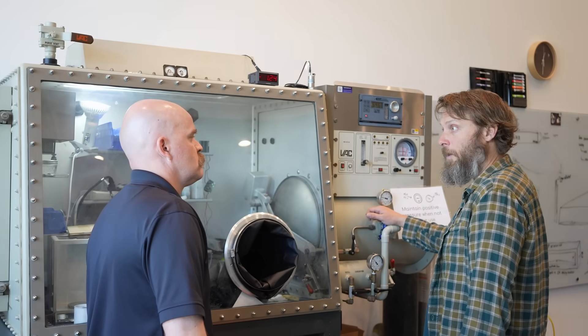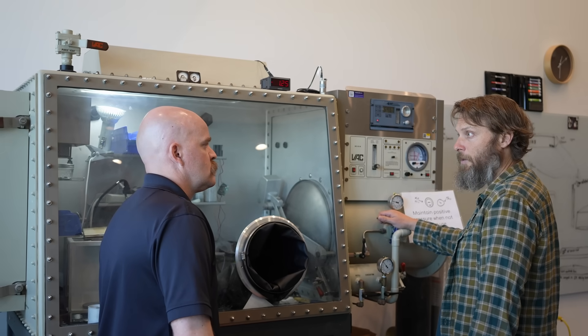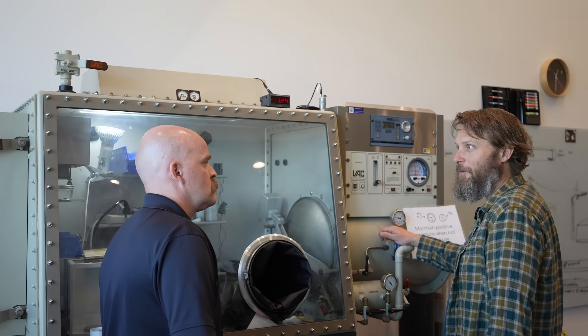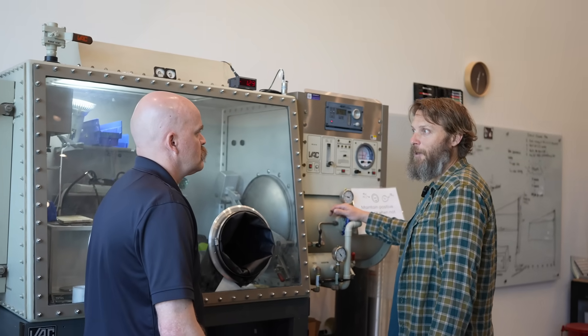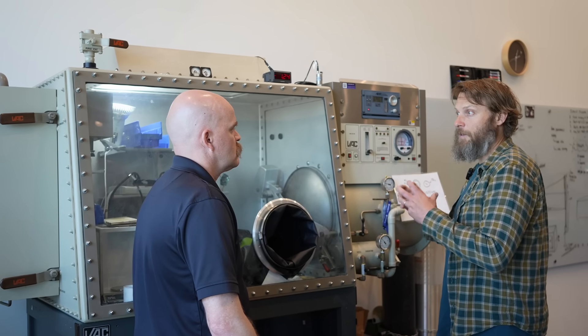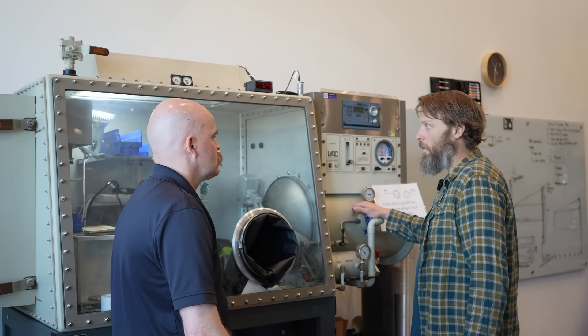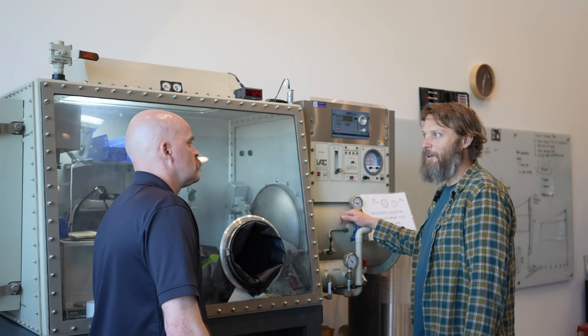You can embed reference electrodes — a third electrode on the cell rather than just a positive or negative tab — like a lithium metal reference electrode. This can show you what percentage of the cell's losses are due to the anode and what percentage are due to the cathode, to help optimize your cell design. Something I love to do with this box is use a lithium fluoride glass slide to put a window in cells so that as you charge and discharge, you can observe the color change of the graphite material — it turns from black to silvery, then to a gold color when reaching max lithiation. Even a jar closed in here becomes an Argon environment for working with a sample.